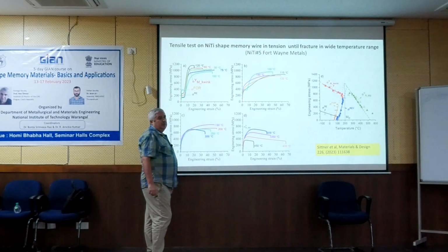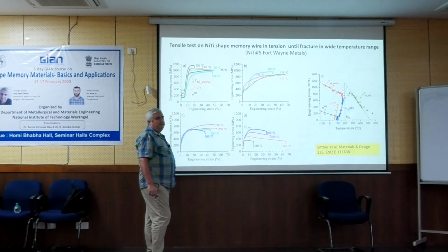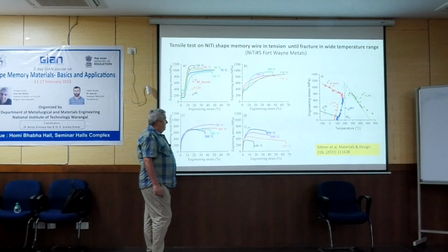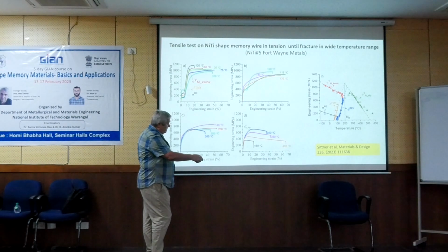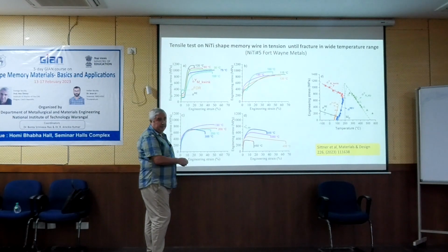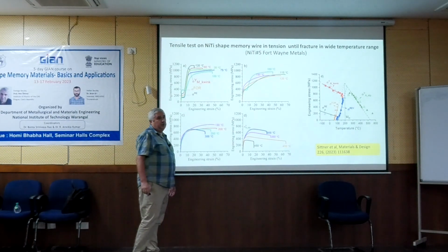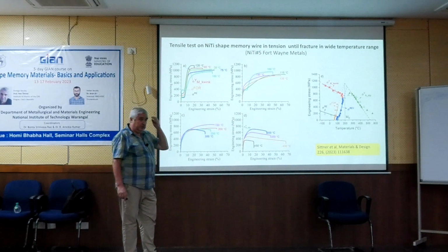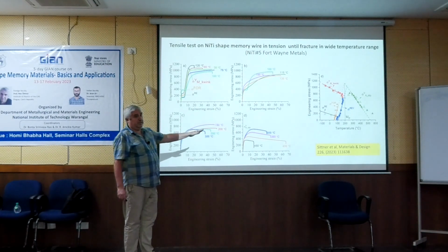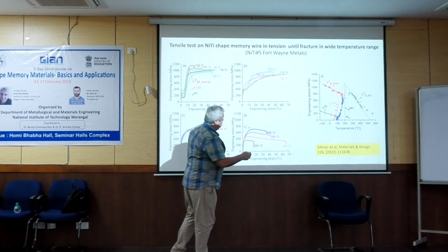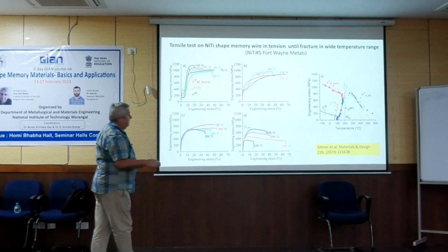How do we make plasticity models for this kind of curve which declines after UTS? Straight softening will do the work, basically. The stress softening is this, and it shows that the strength softening is independent of temperature. So this is something you can put into the model, and then you have experimental evidence for this decrease of UTS. That's all you need to model the plastic deformation. But we don't bother much with that. We only include it into the scheme so we understand what's going on in the wire.